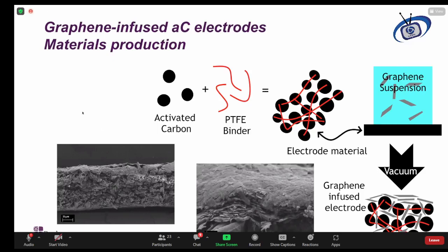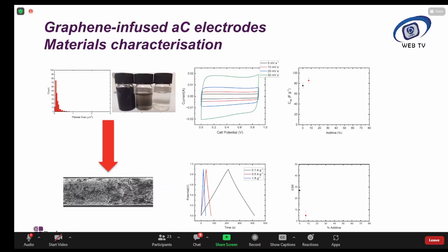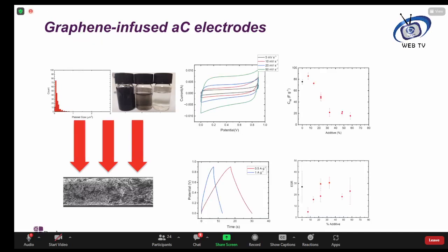If we undertake measurements of the electrochemical performance of these particular graphene-infused supercapacitor electrodes using graphene with a relatively narrow-sized platelet size distribution, we find that compared to an undoped activated carbon electrode, that is a carbon electrode with no conductive additive, there is a small increase in the specific capacitance, but a very large reduction in the series resistance. And reducing the series resistance will increase the power output of the supercapacitor, thereby increasing its performance. So what we did quite naturally was increase the amount of few layer graphene that we infused into the activated carbon electrodes, and we found that actually there was a fairly steep drop after an initial small quantity was added, and the resistance of the supercapacitor electrode increased.